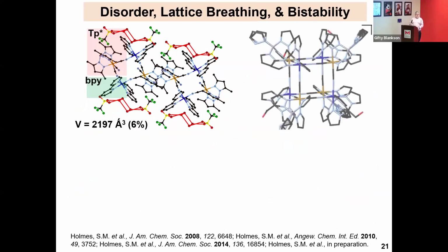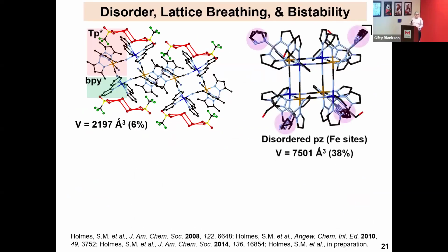All right. Lattice disorder and breathing. Basically reiterating what I've said all along. If things are crystallographically ordered and you have close contacts between the reactive bits in the unit cell, you don't see any electron transfer. In the molecular box, we had disorder at these uncoordinated pyrazoles, and that was weakly interacting with its environment. We saw electron transfer. I highlight that the volume of solvent around the cluster is large,